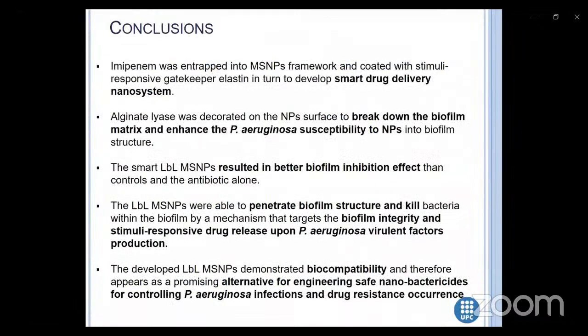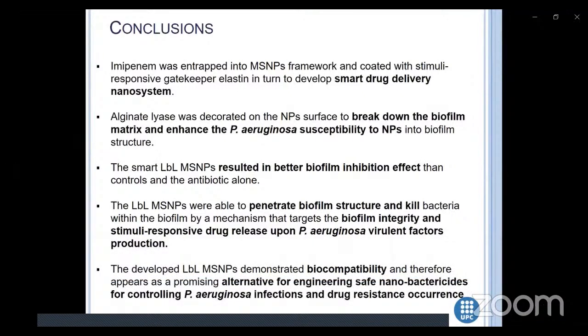So we can summarize that the imipenem was entrapped into a mesoporous silica nanoparticles framework and coated with stimuli responsive gatekeeper elastin in turn to develop smart drug delivery nanosystem. Alginate lyase was decorated on the nanoparticle surface to break down the biofilm matrix and enhance the bacterial susceptibility to the nanoparticles into biofilm structures.